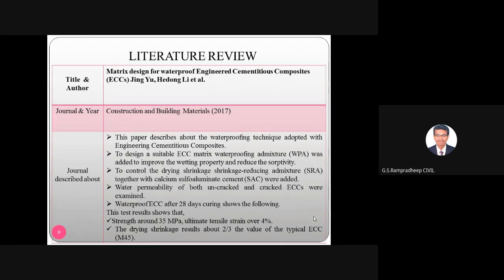And waterproof ECC after 28 days curing shows the following: strength around 35 MPa, ultimate tensile strain over 4%. It's good, a better resistance effect, and drying shrinkage results about 2/3 the value of the typical ECC for the M45 grade concrete. Right? So the behavior seems to be good due to the addition of the waterproofing chemical, in addition to the SRA shrinkage reducing admixture as well as blending with calcium sulfoaluminate.